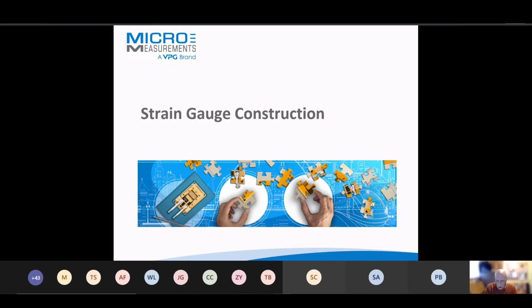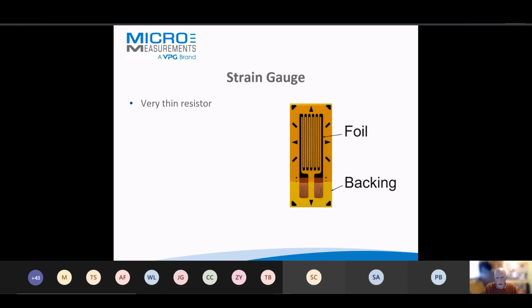So what does a strain gauge look like? Let's look at the construction of a strain gauge. It's pretty simple. We have a thin resistor. Okay, I'll put in the "very thin" in there, we'll come to that in a minute. We've got a foil on some sort of non-conductive backing, somewhere around 25 to 70 microns. It does depend on the actual gauge type. Some are thinner, some are thicker. This will be considered a typical range. These sensors are bonded to a structure using some process that we will review very briefly. And this will accurately follow the structure's deformations, and it will give you a resistance change as the strain changes.